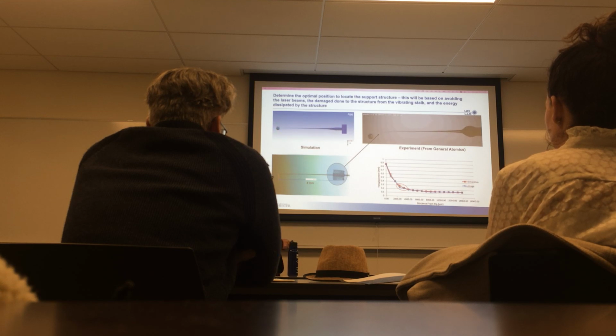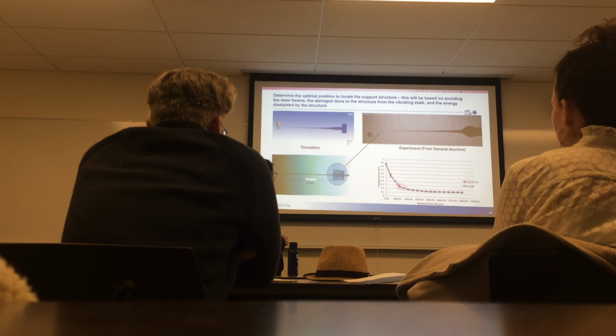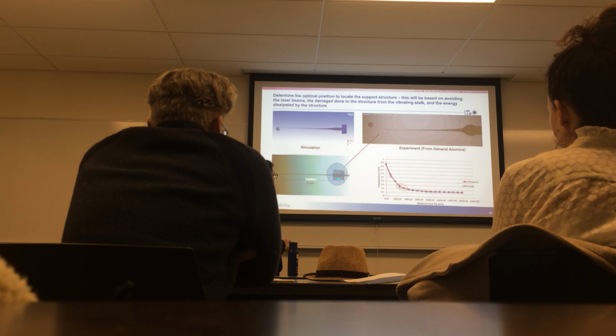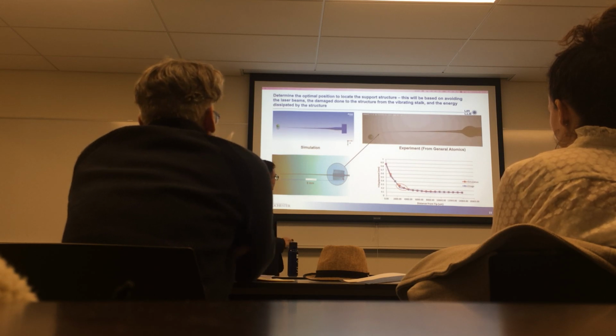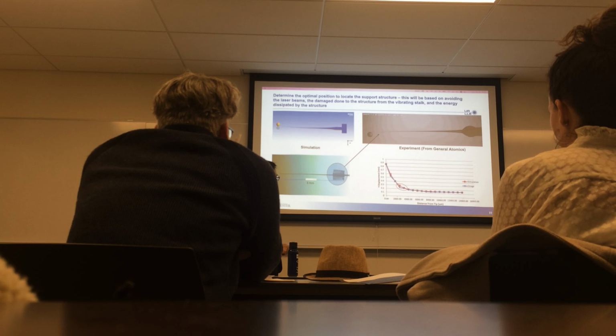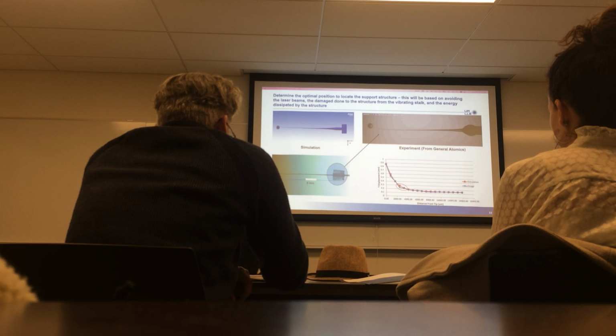The first reason is that in these areas, the foam structure doesn't have contact with the capsule. The second reason is that in this area, the foam structure will not block laser beams during laser experiments. The last reason is in this area, the fuel tube still has a large displacement. So during inner vibration, the foam structure still can contact with the fuel tube to dissipate energy. So after we figure out the best location, we will assemble this structure together.